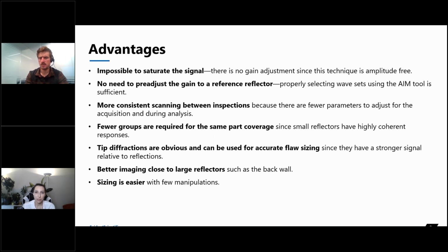So properly selecting the wave set that we need is important. We can do that with the AIM tool, but there's no other calibration really needed for this method in comparison to a TFM with amplitude. So that means that it's more consistent scanning in between inspection, in between inspectors as well, because there are fewer parameters to be adjusted with this technique. So the acquisition and the analysis will be more consistent.